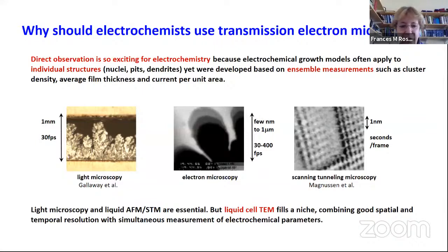So there's a lot of ways of doing this kind of microscopy. Light microscopy is a fabulous way of getting good images of things as they change, with high time resolution. Of course, the spatial resolution isn't so great. Scanning probe microscopies can give you excellent spatial resolution, but typically, because the probe physically has to scan, it takes time. I know there are some fast ways of doing it, but generally it's a slower process, especially for rougher surfaces.